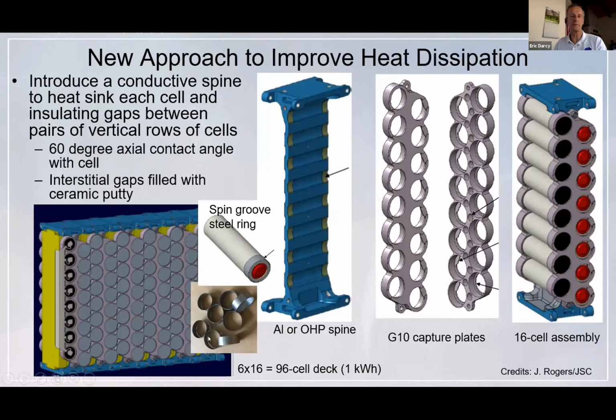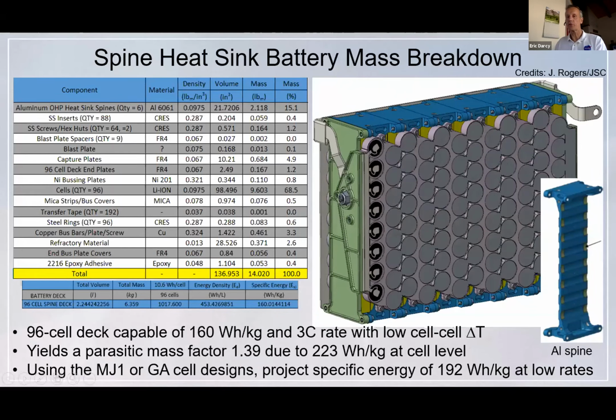We also put stainless steel rings around the spin groove of the cells, which our previous studies have shown is the most vulnerable area of the cell for sidewall rupturing. You put 6 of those 16-cell assemblies together in what we call a battery deck with 96 cells, and we're able to achieve 160 watt hours per kilogram with that Samsung 30Q cell. If you don't have a high rate application, you can get 192 watt hours per kilogram by using a high energy cell and running it at lower rates. But we're specifically looking at high rates here.